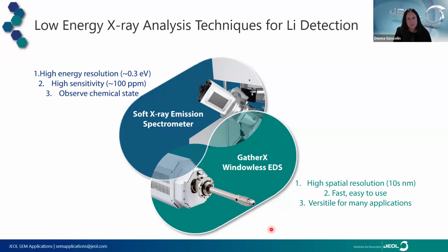And we can work at very short working distances too for very high spatial resolution, so it's versatile for many, many different types of applications. The second detector I want to show you some examples from is our soft X-ray emission spectrometer. This is very unique to JEOL, and it measures low energy X-rays in the soft X-ray region. There are many resonances in this region, and with this detector's very high energy resolution, it's like 0.3 eV at the aluminum Fermi edge, and the high peak to background, we get very high sensitivity.